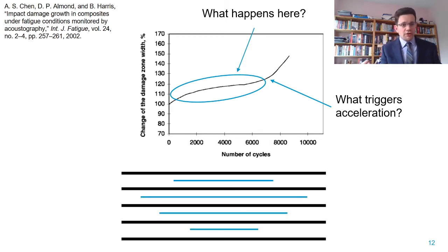If we have an actual laminate with delaminations at each interface—typical for an impact case—and we look at the projection, the width we see will be the width of the largest delamination, because that is the one that will be projected. So we might have actual delamination growth at the lower-lying areas, but the width of the projected zone will only increase by small amounts based on the second delamination.